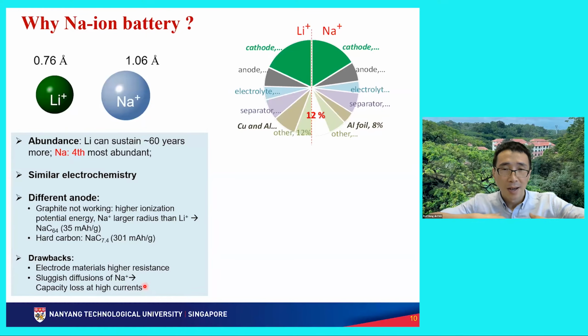Because if you want fast charging and fast discharging, ions have to go in a lot faster, but the ions cannot move in too fast. So it becomes a limiting factor. Therefore, usually the sodium battery cannot have very high charge and discharge capabilities. Also, the electrode materials, especially the cathode materials for sodium batteries, are usually less conductive compared to the cathode materials for lithium. So even though you put in carbon additives, you may have to put in more conductive carbon additives in order to improve it.